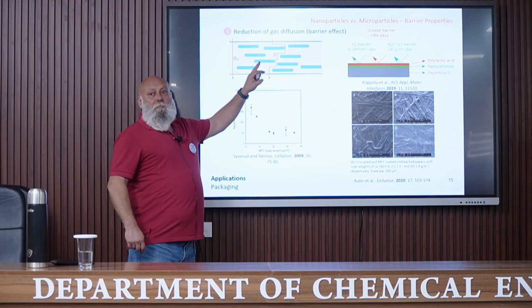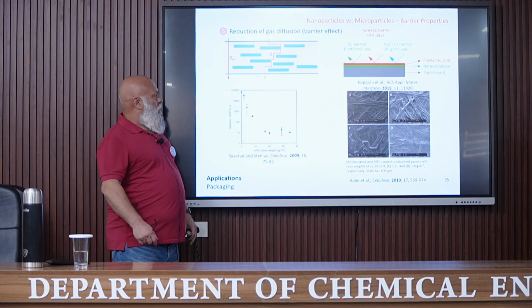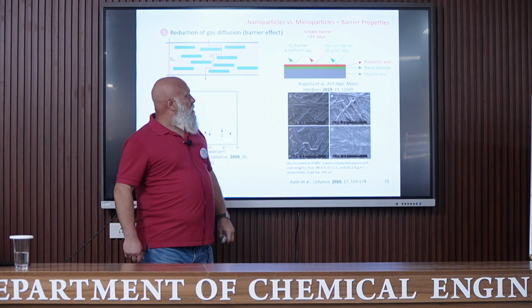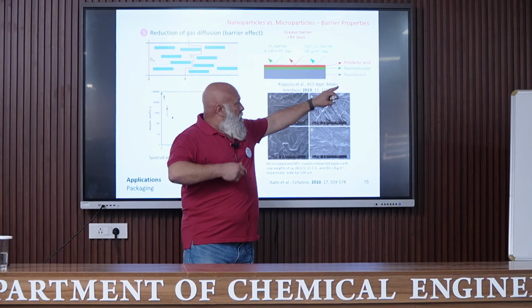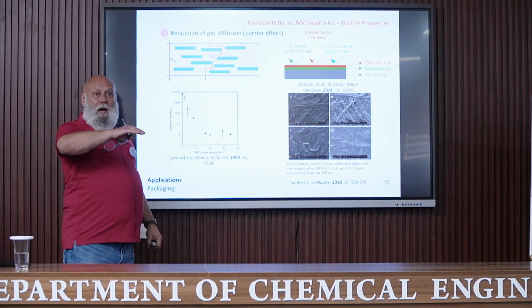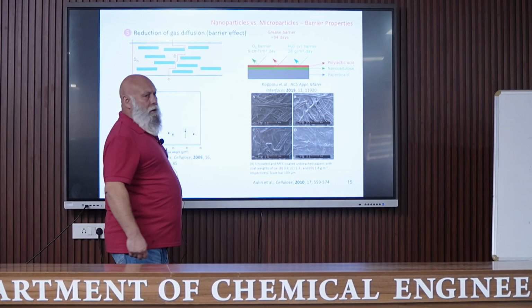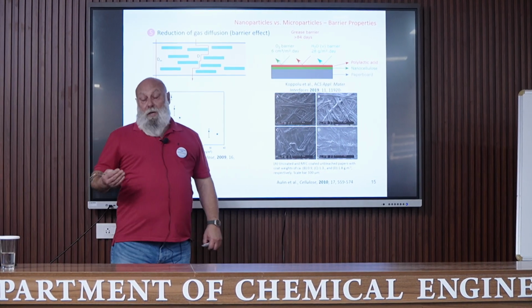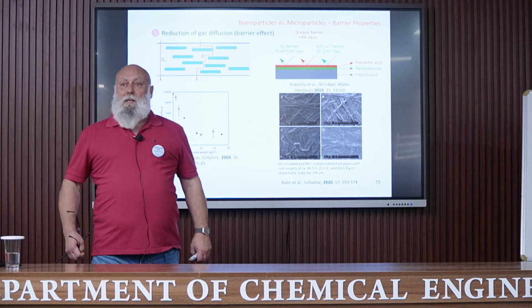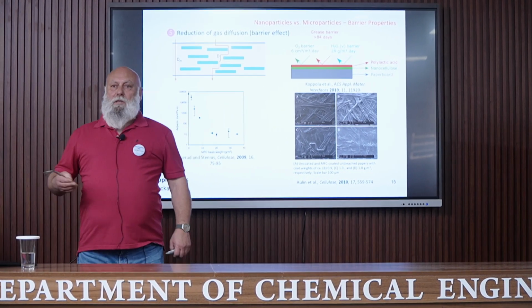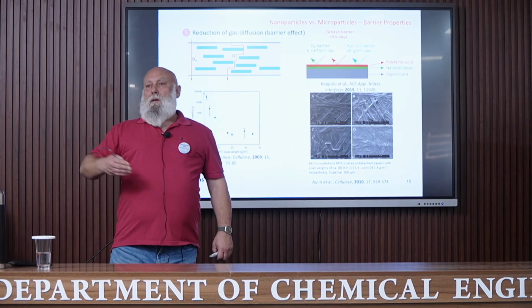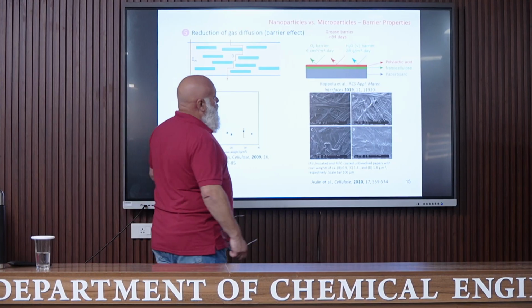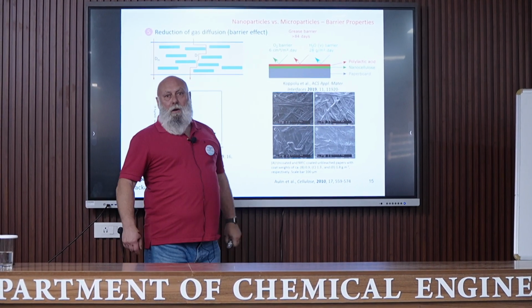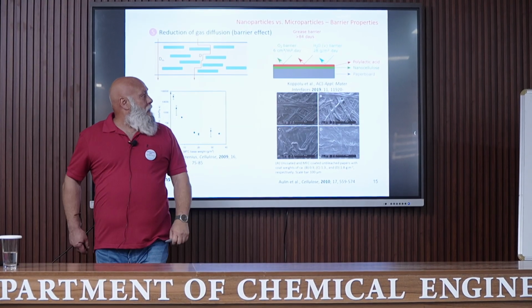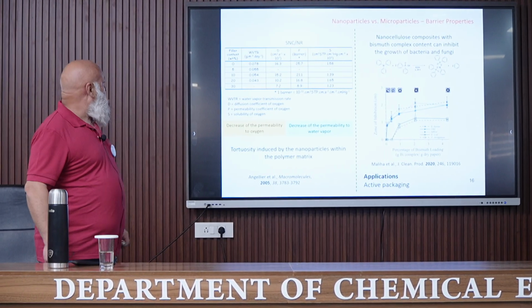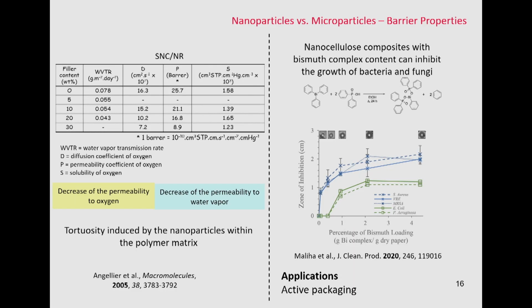So these nanoparticles can be dispersed in the matrix to provide mechanical properties, or they can also be coated on the surface of a substrate that can be a polymer, but also paperboard. We can add a layer of cellulose nanocrystals or nanofibrils to improve the barrier properties, but of course, the material is highly sensitive to water, and the permeability to oxygen will be increased in high relative humidity conditions. To avoid this, generally, another layer of a hydrophobic polymer, polylactic acid in this case, can be added. So these are some examples of barrier properties.